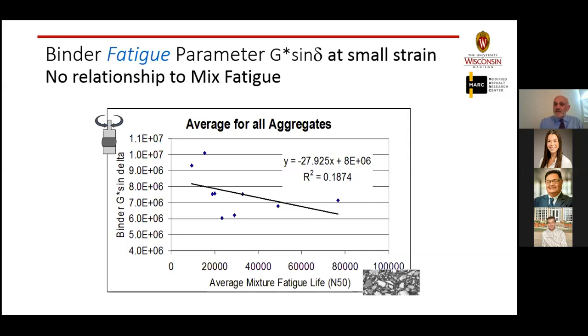What's important is the first step, to recognize there is some problem with the small stress, small strain test like the G star times sine delta. Here is the fatigue life of mixtures, and here is the binder G star times sine delta. There is absolutely very little relationship. As you can see, whether you like the R square or you don't like it, it's not important. This is almost a scatter plot. And in fact, if you look at these values, you can hardly tell which material you should be selecting based on these values and so on.